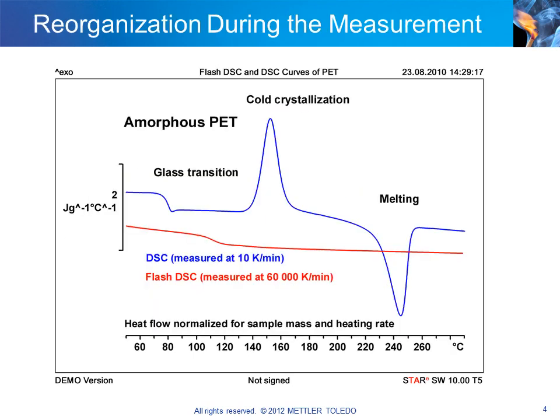The slide shows two DSC curves of exactly the same material. The blue curve, measured at 10 degrees per minute, shows the glass transition, cold crystallization, and melting that we discussed in the previous slide. Cold crystallization and melting are reorganization processes that occur during heating. The red curve was measured at 60,000 degrees per minute and looks very different. It shows that a complete measurement result is only obtained when the material is measured at this much higher heating rate. At this heating rate, only the glass transition is observed.